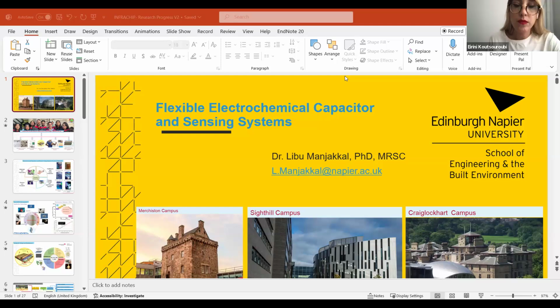In the frequency aspect, we are mainly using 1 millihertz to 1 megahertz. Of course, we have the facilities here to do the 1 microhertz to 10 megahertz range. The problem in the 1 microhertz range is the long time needed for the measurement. So the majority of the work we reported is in the 1 millihertz to 1 megahertz range. The reason for the low frequency range is that only there can you observe the exact electrode ionic diffusion part.